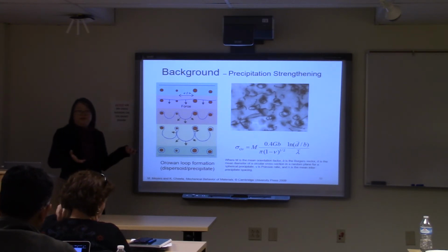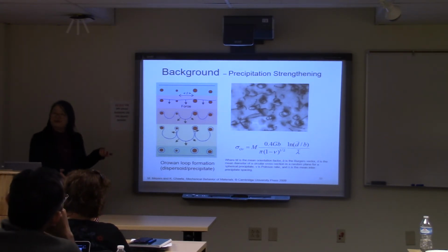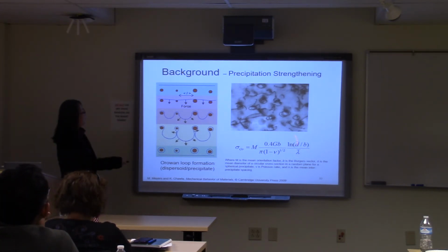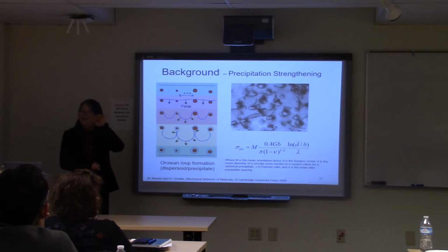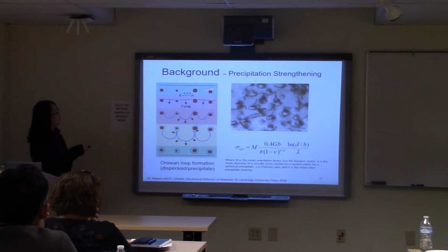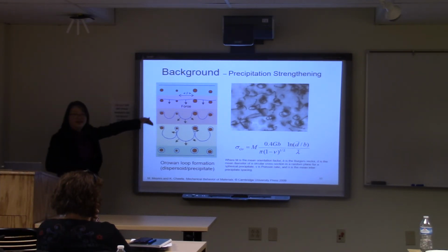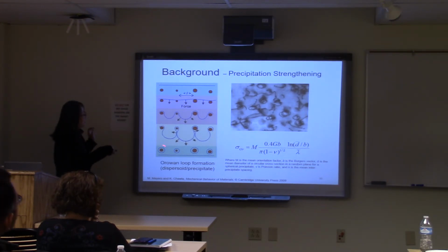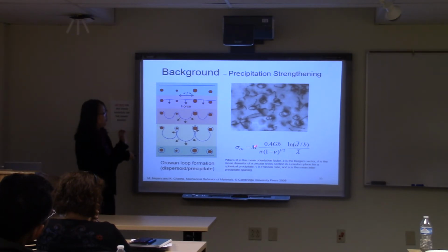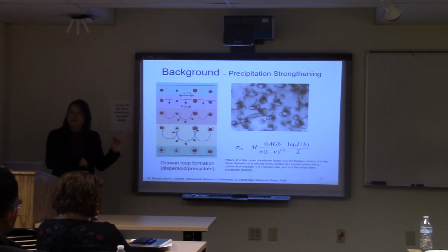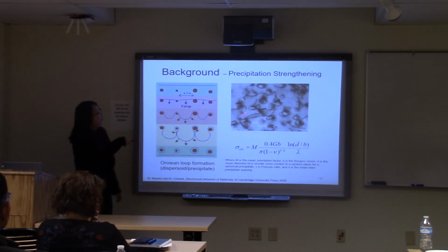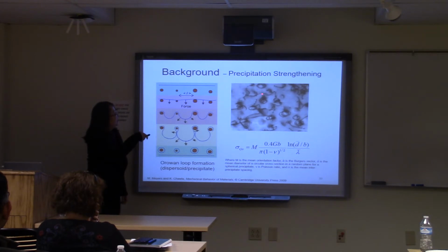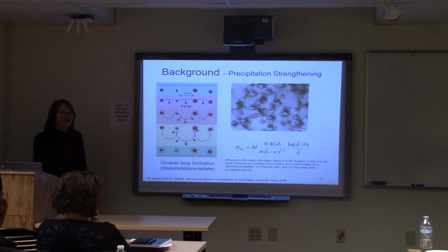This is just giving you, some of you might have a mechanical behavior background, an idea for the students of how those precipitates, those small dots, contribute to the strength. If you have those small precipitates and then one dislocation line moving here, those precipitates can play a role in stopping and impeding the motion of the dislocation by forming those Orowan loops. And there is also an equation governing these mechanisms. On the top right, it's where those precipitates really look like and how you see the dislocation loops forming, giving you an idea about this.